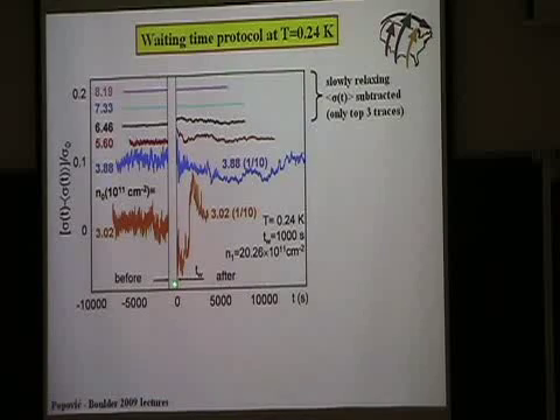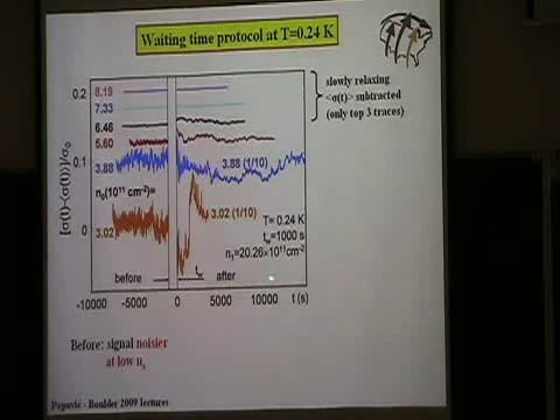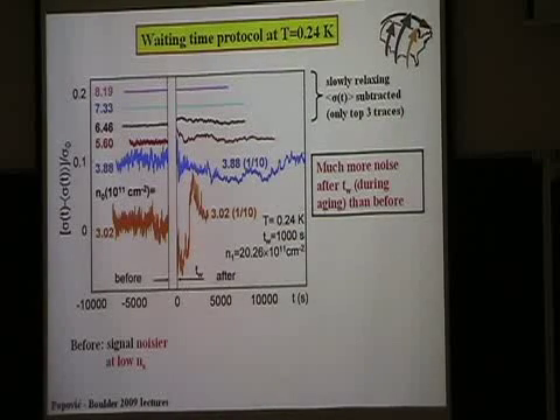And then when we change the density during the waiting time and we come back to the same densities here, at these high densities we see some relaxation, which we actually subtracted from the top 3 traces because we wanted to focus here on the noise. And you can see that after this perturbation, the noise is much bigger than before. In fact, so much bigger that for these two lowest densities we divided the signal by a factor of 10. So after the perturbation, during this aging process, signal is much noisier than it was before the perturbation.